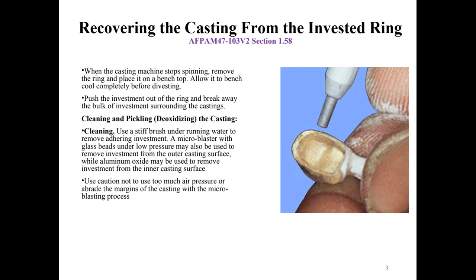Always use caution to not use too much pressure when we use the sandblaster, because that can put a lot of stress on the dental alloy. Also, if we keep the tip of the sandblaster in one area of the coping, we can poke a hole through it. So always make sure that you use the recommended pressure for the sandblaster, and always move the tip of the sandblaster around until everything gets cleaned up.